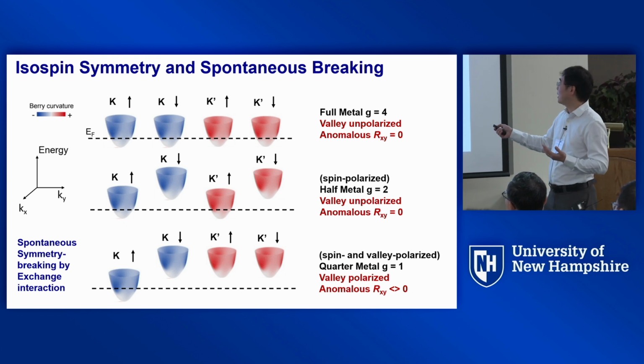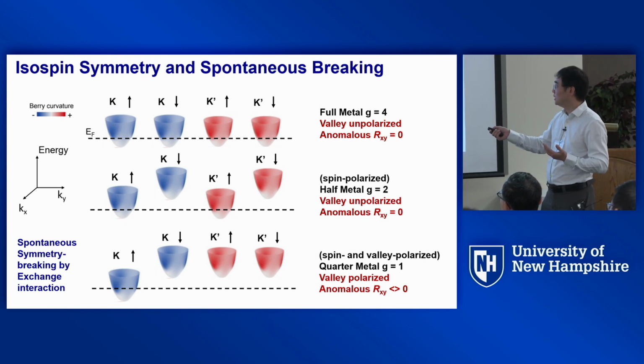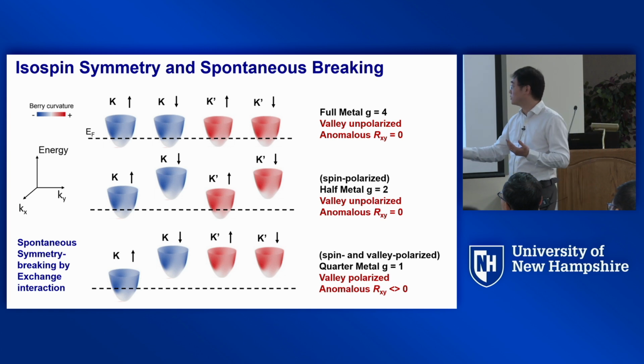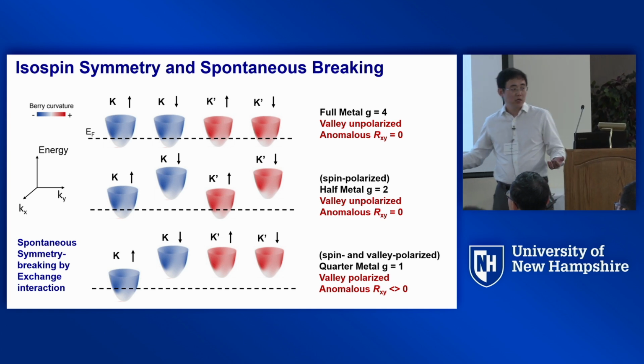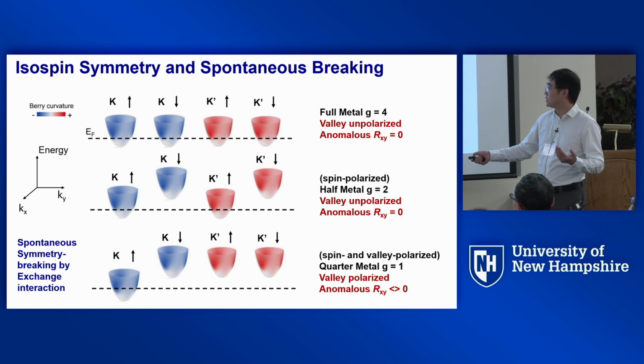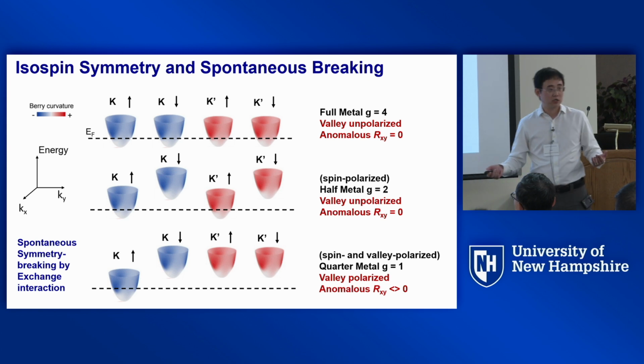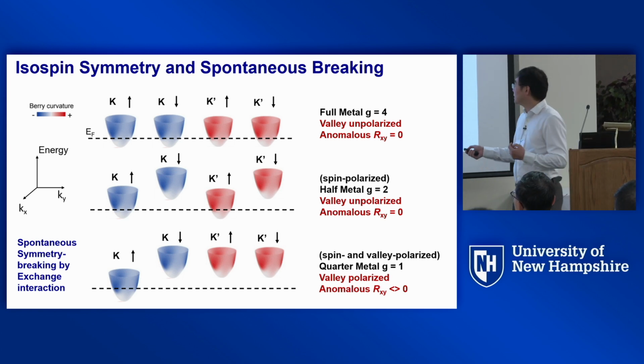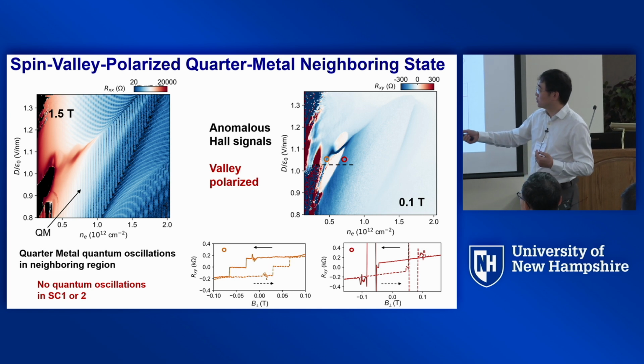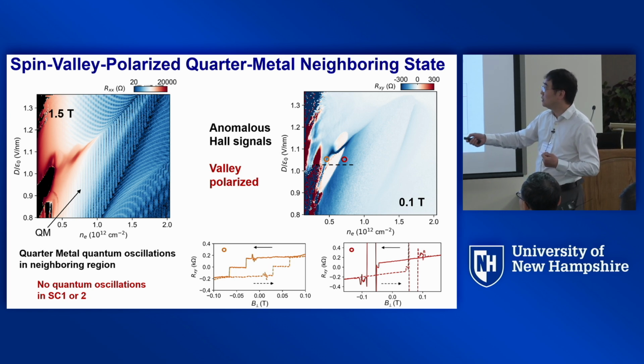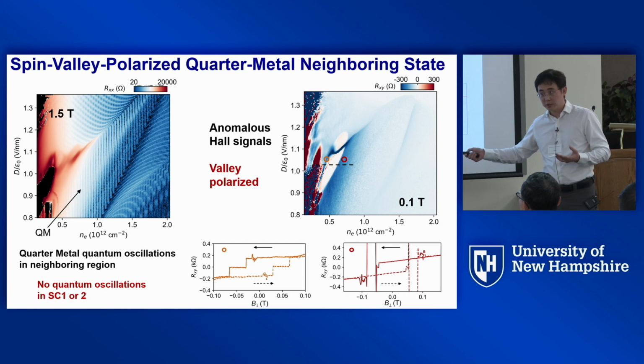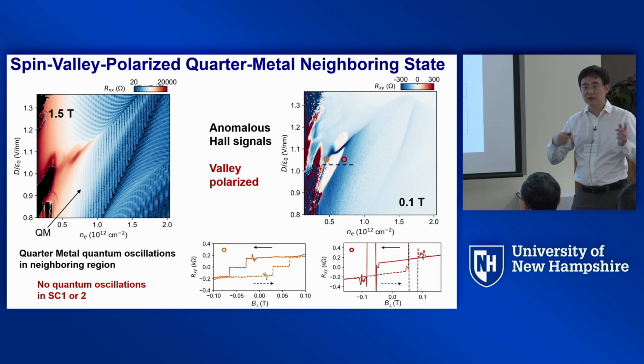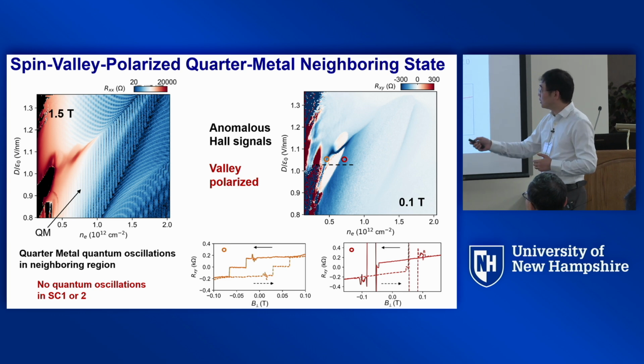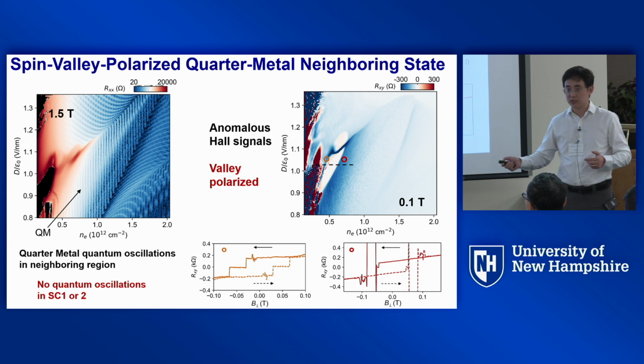For example, you could get a half metal, meaning 2 out of the 4 are populated, or you can get a quarter metal, which means 1 out of the 4 is populated. As you can imagine, if you have 1 out of 4 populated, then most naturally you have spin and valley polarization in that pocket. Then you have a net Berry curvature and anomalous Hall signal. And experimentally, I was showing you quantum oscillation. The period of quantum oscillation here actually corresponds to a quarter metal because we can just count Landau levels, which have a well-defined degeneracy, right? It's a quarter metal. It has anomalous Hall. So it feels like this part, at least, is a spin and valley polarized quarter metal.